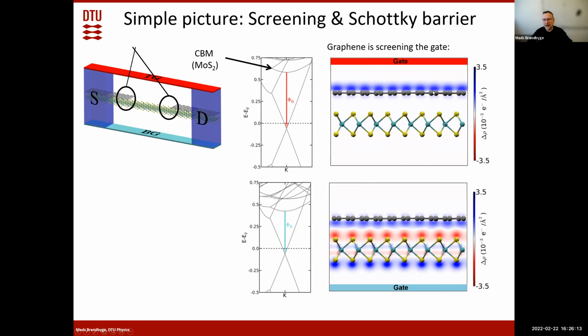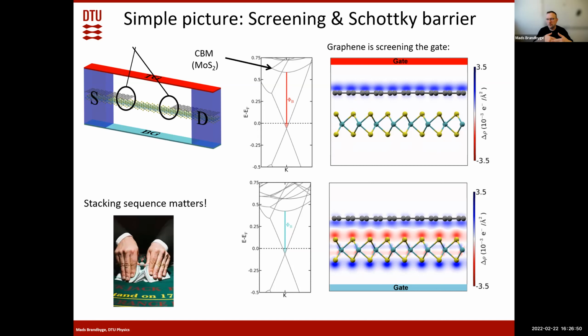If we have the gate, the graphene and the MoS2 in this sequence, then the graphene, because it's semi-metallic, is screening out the effect of the gate. So it's not shifting down the conduction bands of the MoS2. But if we have the gate, the MoS2 and the graphene, then the MoS2 is sitting in the capacitor between the graphene and the gate. In this case, we are much more effectively shifting down the conduction bands of the MoS2. So the upshot is that when you make stacks to make transistors based on 2D materials and you use graphene in the stack as the electrode, then the stacking sequence matters. And this is actually a nice thing, because it means that the gate is only effective from one side in the stack. So we can have different stacks with transistors where the gate is only acting for transistors in one direction, which is kind of nice.